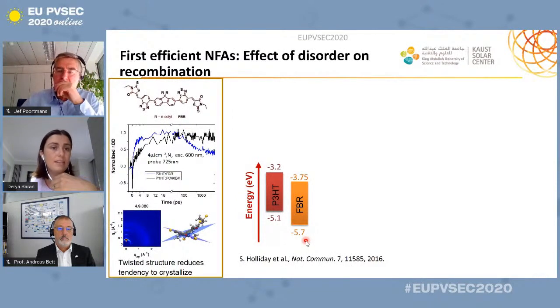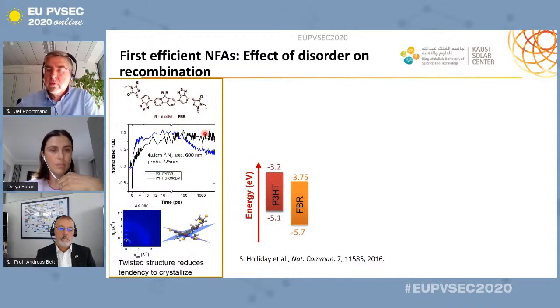And for this reason, NFAs came at the right time, I would say, just when I was having my postdoc back at Imperial College. And then this beautiful simple FBR was synthesized. And when we compared it with PCBM, we have seen a very fast rise in the polarons, and it was working efficiently as a solar cell. But when we look at the long time dynamics, we have also seen that these polarons were actually disappearing and it was not as good as P3HT:PCBM, although we got around 4% efficiencies. And it was simply because of this twisted structure of the FBR that reduces the tendency to crystallize.